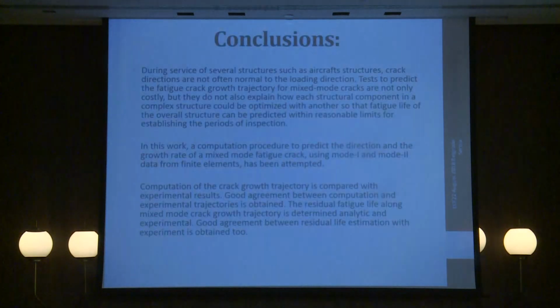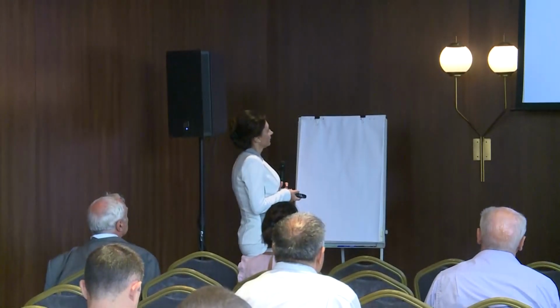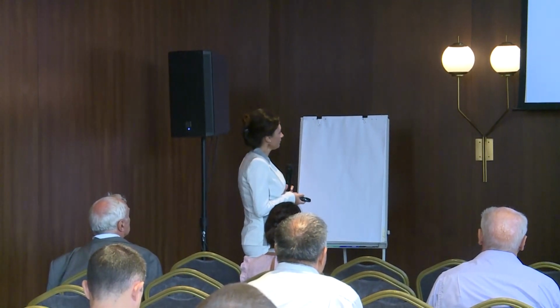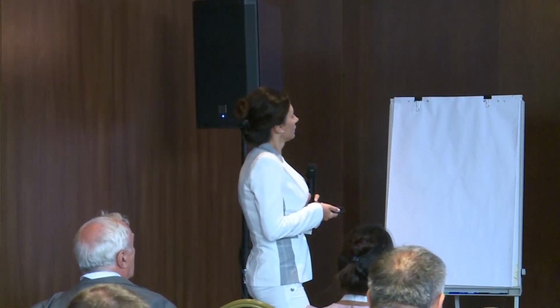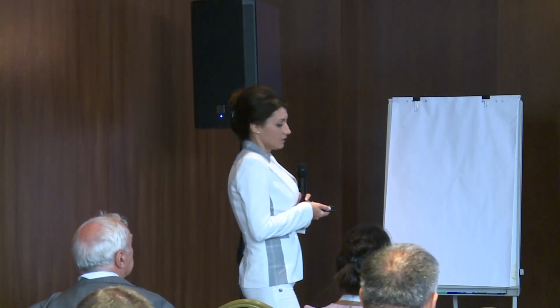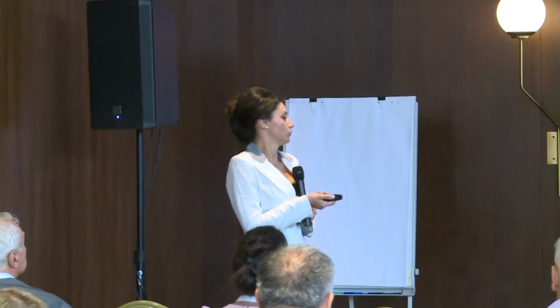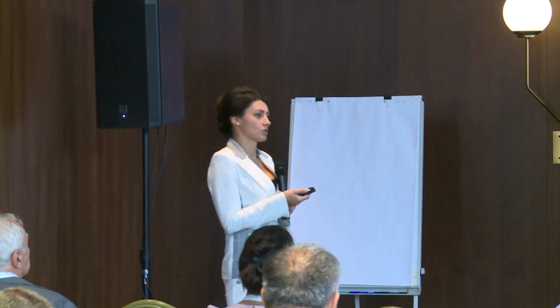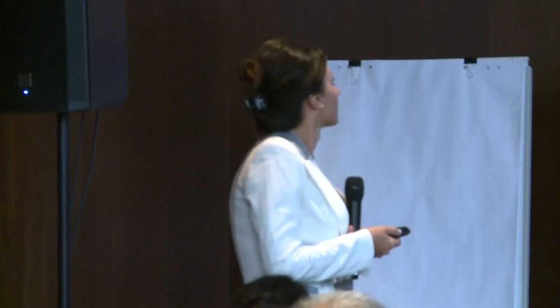For the conclusion, I can say that in this work a computational procedure to predict the direction and the crack growth rate of mixed mode fatigue cracks using mode 1 and mode 2 data from finite elements has been attempted. We have very good agreement between the results from numerical simulation and the results of experimental testing, and we can use these results for every complex structure or part of a structure, be it aircraft structures or something like that. It can be used for any mechanical structures.